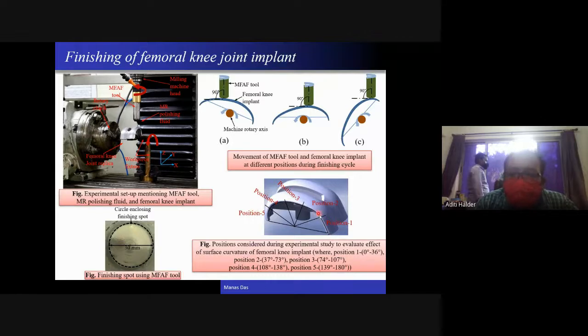Like this, there are a total of 5 sections we have divided, because the spot diameter we have measured here is around 30 millimeters. When this tool is touching the working surface, a spot diameter is generated on a flat surface, around 30 millimeters. So these individual sections are less than 30 millimeters. Initially it will do the polishing here, then it will rotate, and then the polishing tool will come over there. Like this, a total of 5 sections will be polished in one line.